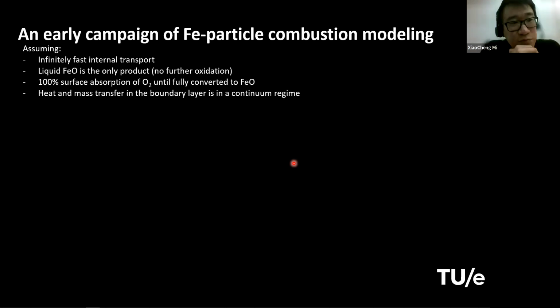So we made the following assumptions. We assume that the internal transport is infinitely fast, so that we eliminate that as a rate limiting factor. And we assume that inside this liquid particle, FeO is the only product. Once all the iron is converted to FeO, meaning the molar ratio of oxygen inside the particle is 0.5, we just assume that the reaction is over, and the particle cools down inertly. Also, on the particle surface, we assume 100% absorption of oxygen. As long as an oxygen molecule can reach the particle surface, it can be absorbed into the particle.